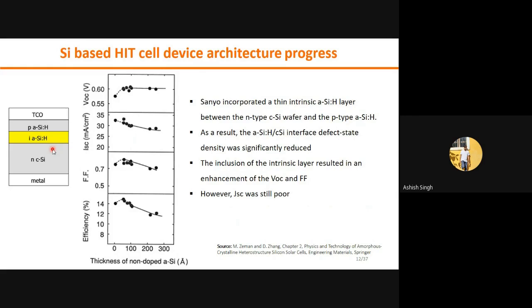Then what they did, they took the N-type silicon wafer, they put a passivation layer, intrinsic amorphous silicon, and then P-type amorphous silicon and TCO. So a significant difference they observed: VOC improved up to 600 millivolt, current density is still struggling, and fill factor also improved, and they could make approximately 14% efficiency. In this condition, they changed the thickness of the passivation layer from a few nanometers to approximately 25 nanometers. Yeah. And still the current density was poor.